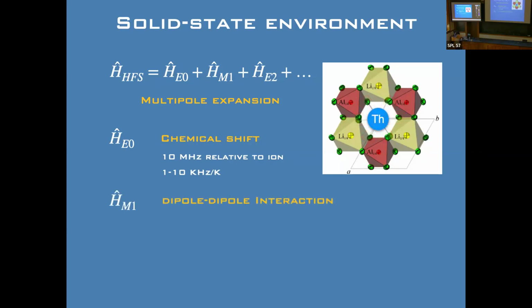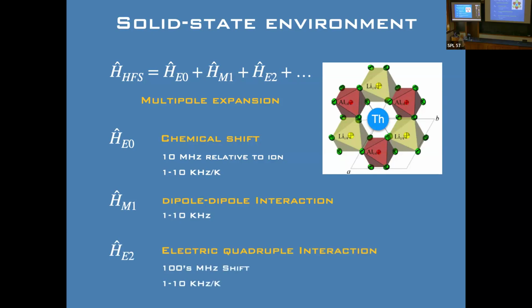The next term, this H_M1, is just a dipole interaction. Thorium-229 has a nuclear magnetic moment, and there are a lot of fluorines in all the crystals that have been used so far, which also have spin. So there's some interaction there, and that gives you a broadening of the transition of order a kilohertz to 10 kilohertz. And then there's the electric quadrupole interaction. The nucleus has an electric quadrupole moment, and the crystal clearly makes an electric field gradient, so there's an interaction. That's the largest shift, but it's just a shift if everyone substitutes into the same site, and it's also a little bit temperature dependent.